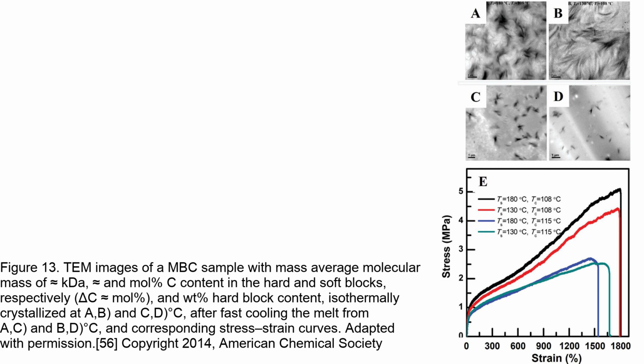The size and number of crystals are observed to be larger for the samples quenched from a heterogeneous melt compared to those from a homogeneous melt. This indicates that at a crystallization temperature of 108 degrees Celsius, the crystallization of the sample quenched from a homogeneous and a heterogeneous melt occurs almost unrestricted, with the crystallization rate being higher than the rate of mesophase separation.